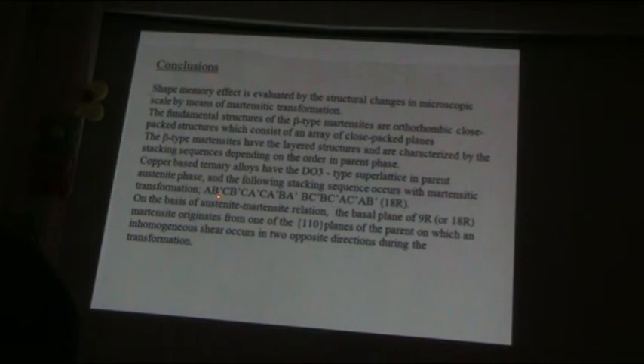transformation: A, B, C, C, B, C, A, C, A, B, A, B, C, B, C, A, C, A, B, like that. On the basis of the phenomenological theory, the basal plane of 9R or 18R martensite originates from one of the close-packed planes of the parent, on which an inhomogeneous shear occurs in two opposite directions during the martensitic transformation.